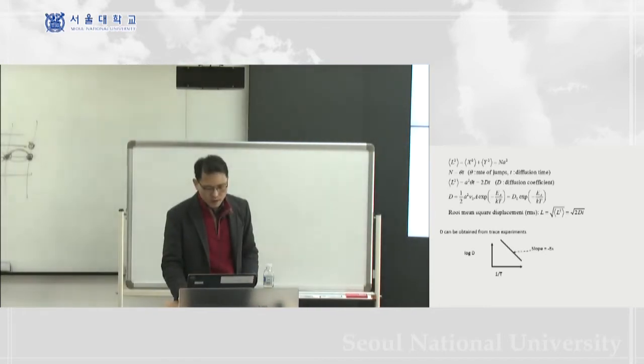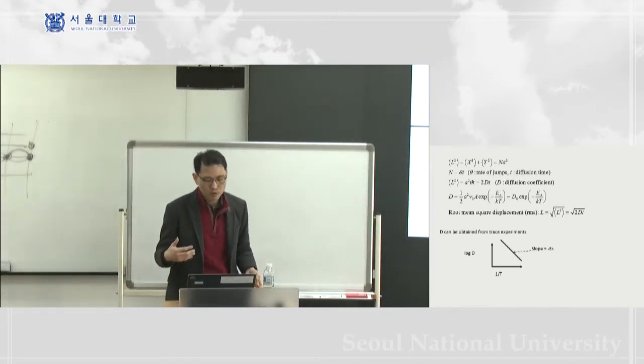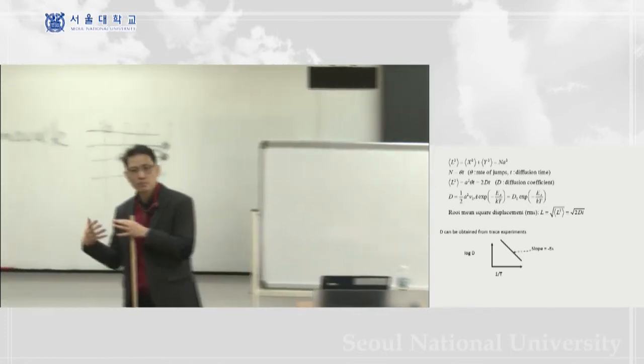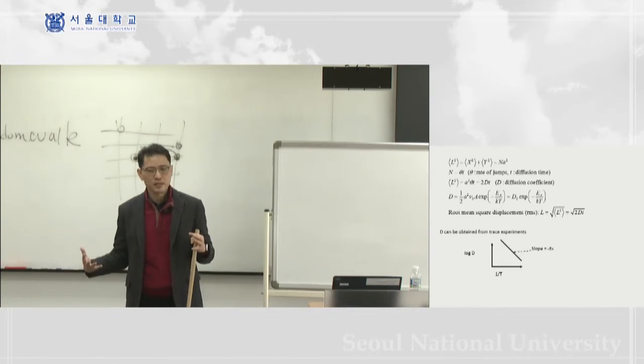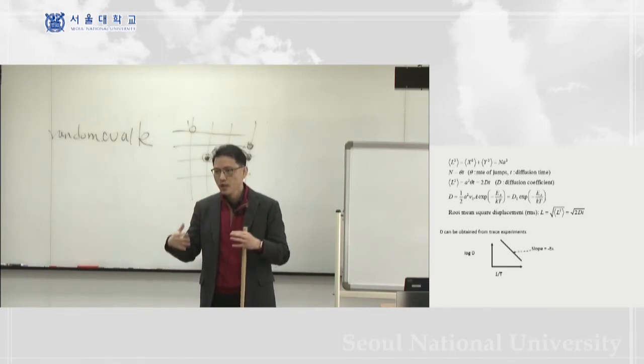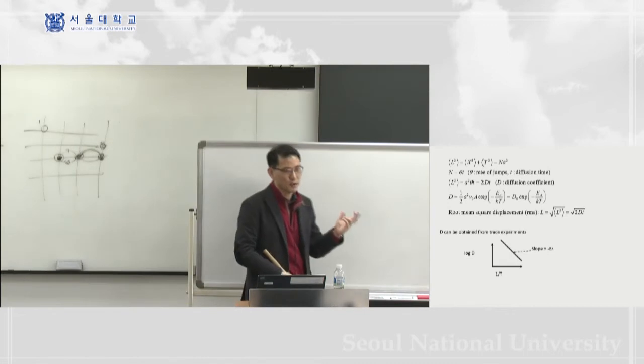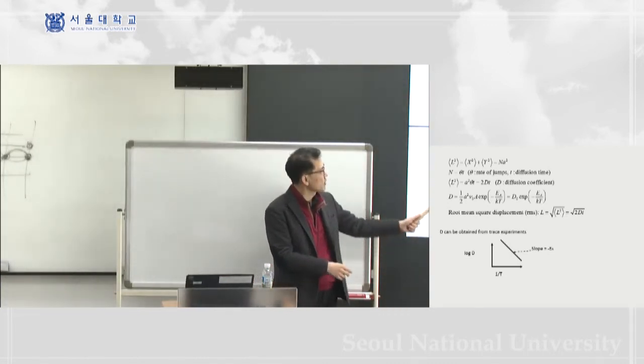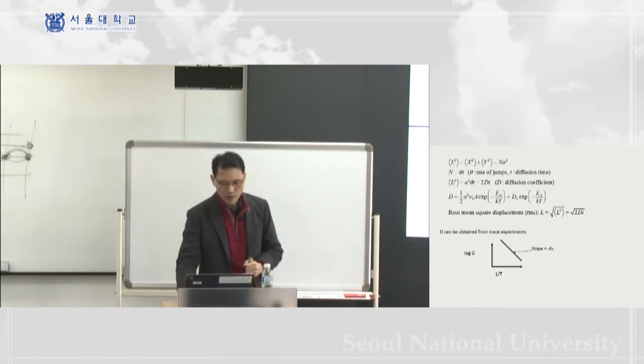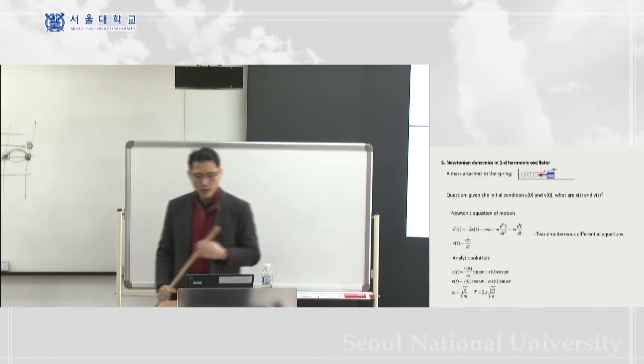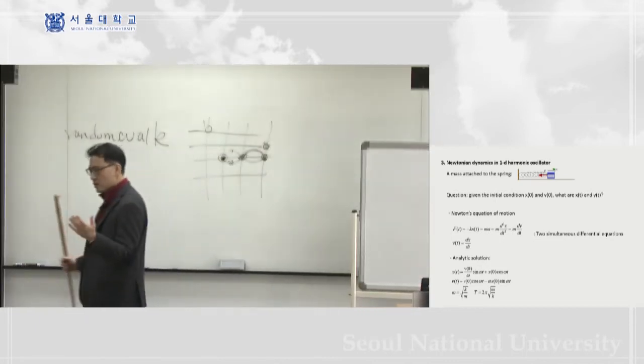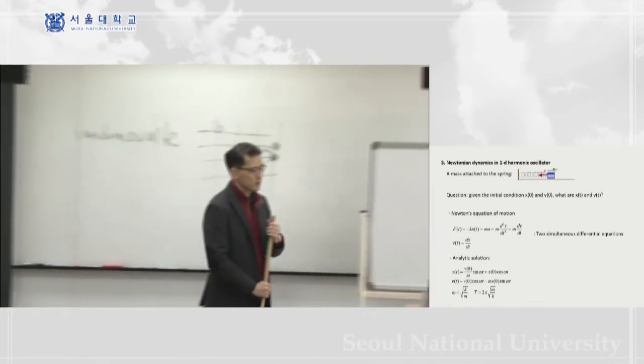All right, so that shows how we address the same problem using the atomistic viewpoint, right? It's much more complicated than Fick's law. You have to go through many different and very complicated calculations. However, what we obtain here is a very precise theory, without any empirical parameters. So that's the strong point of atomistic simulation. It is very general, and it can be used in various kinds of configuration, not just the solid, but also the grain boundary or the surface. So that was the comparison between continuum simulation and atomistic simulation.